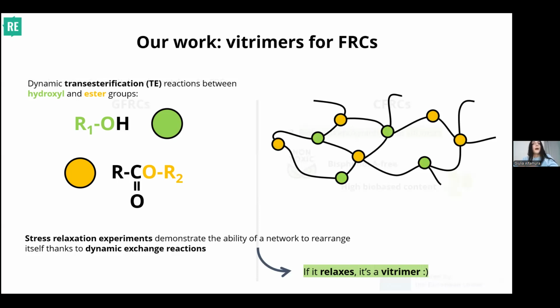But how can we say that a vitrimer is a vitrimer and not just a thermoset? This can be said by just a simple experiment called stress relaxation, in which a constant deformation is applied to the material, and we just monitor how the stress and so the modulus changes over time. If it's a vitrimer, thanks to the dynamic exchange reaction, we expect the modulus to decrease. So we can say that if it relaxes stresses, it's a vitrimer.